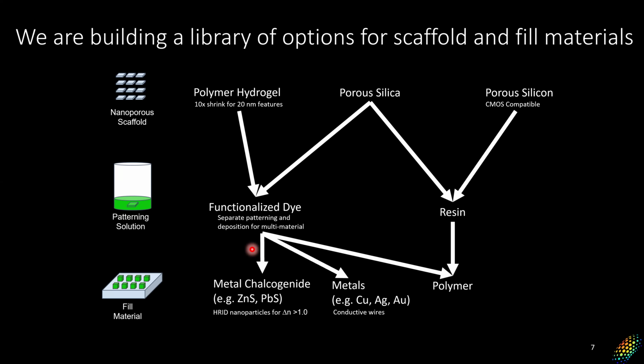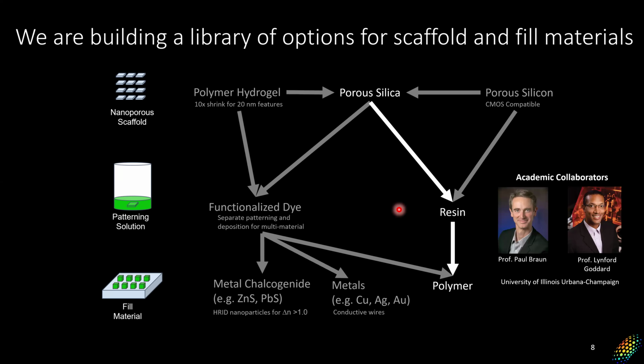What wavelength are you trying to work at? So this really is a function of these materials. This porous silica with polymer is the most mature of our material platforms. A lot of this work was pioneered by our collaborators at UIUC. This works pretty well for the visible through shortwave IR. So these scaffolds, you do get Rayleigh scattering. I'll talk about that in the next slide. So that starts being fairly significant or noticeable down into the blue.